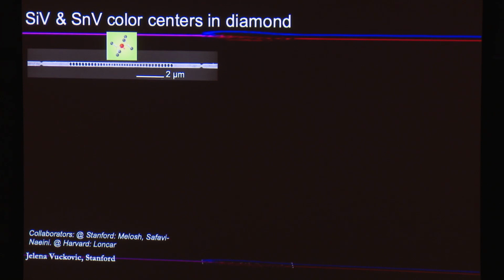So over the past 5 years or so, we've been primarily focusing on color centers in diamond and silicon carbide, as I mentioned. And we made a switch to these color centers because it had been really difficult to handle inhomogeneous broadening of indium arsenide, gallium arsenide quantum dots, which are excellent quantum emitters, but they have very, very large inhomogeneous broadening. So if you were to build a system where you have to interface multiple of these emitters, it's pretty much impossible. And we shifted to other types of emitters where we can have much, much smaller inhomogeneous broadening and tolerate it and control it by a variety of methods.